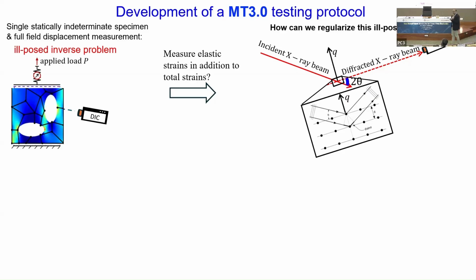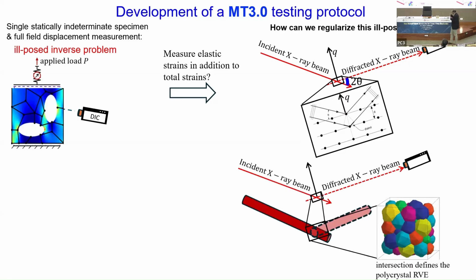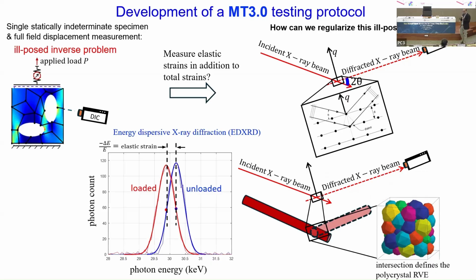Now, you can do that by effectively Bragg's law, which is this idea here, that you have an incident beam, you have a diffracted beam, and basically looking at that diffracted beam, you'll be able to get hold of what is the atomic spacing. Now, in reality, you don't do it for a single crystal, but just like when you're doing a computation, you define some kind of a representative volume element, which is what we have got here. You want to know what is the average elastic strain over that representative volume element inside this material. And that's what we'll do. And what happens there is, as you load this, the energy spectrum, by Bragg's law, will shift from this unloaded state to this loaded state, and that will give you the elastic strain.